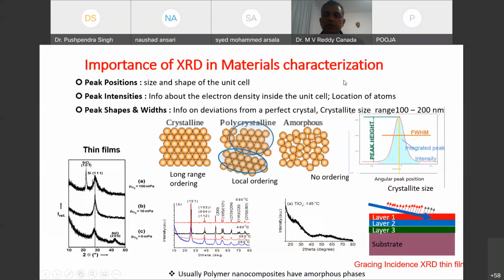So for example, the importance of X-ray is that you would like to see whether your materials are amorphous or nanocrystalline, depending on the crystallinity or the temperature, and we can see differences in the crystallinity or average crystallite size, etc. Usually, if it is a nanomaterial, you can see line broadening, or if it is a crystalline material, we can get very sharp peaks, etc. Also, if it is thin films, we can see what type of layers, for example, different layers, by using glancing angle X-ray diffraction, etc.